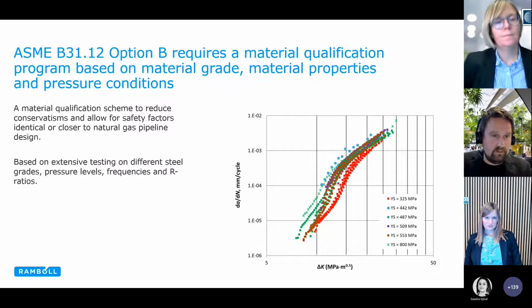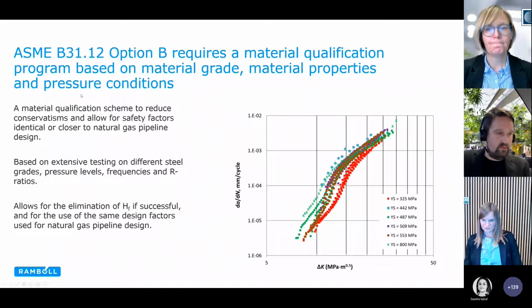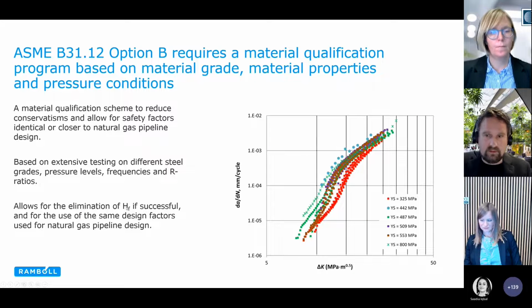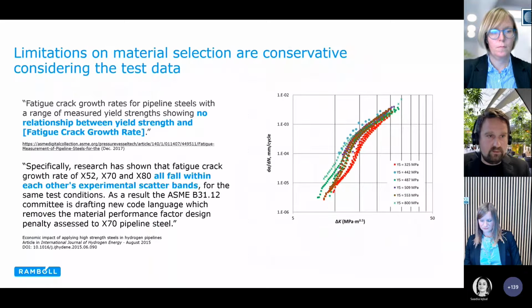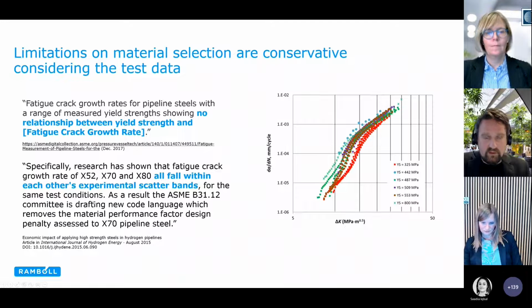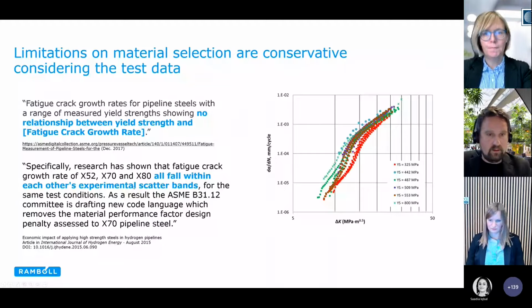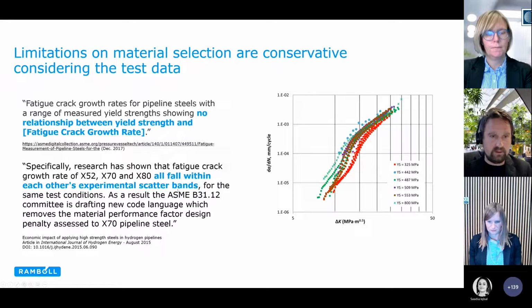And there have been voices, and I'll get a little bit back to that, that the argument could be made that the material performance factor is not fully utilizing the test data we have today. And ASME has even said this themselves, that there is no relationship between yield strength and fatigue crack growth rate. And here's an example of another interpretation, written in 2015, so 4 years before the ASME was updated, that since the data for these different material types fall within each other's experimental scatter bands, the ASME B31 committee is drafting a new code which removes the material performance factor for X70 and below.